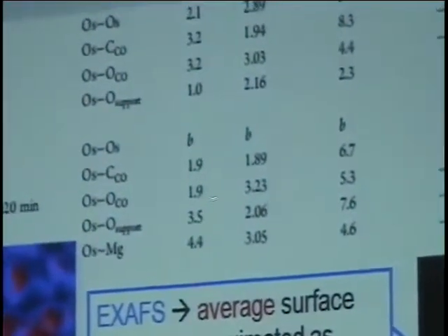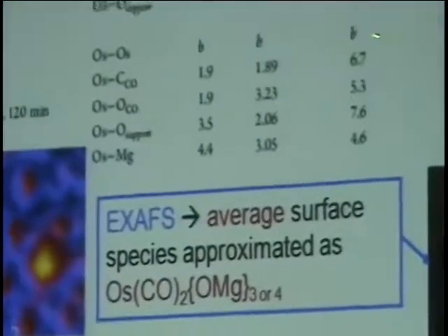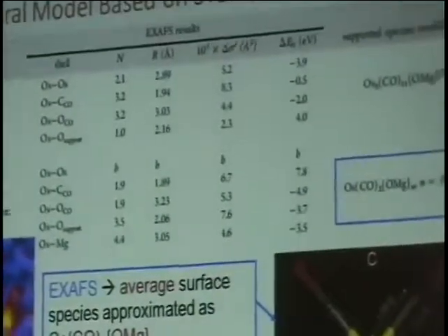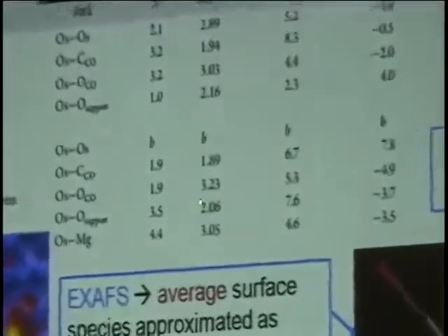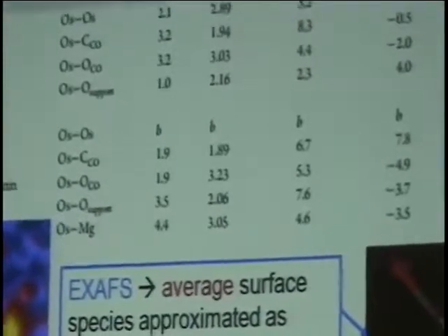And the key that we need to get beyond just the microscopy is the XAFS evidence. So let's go to the mononuclear: we get an osmium-oxygen coordination number over the whole sample, various faces of MgO, of 3 or 3.5. And so what we're inferring on this particular surface is that the value must be about 4. This is, of course, a model. And so we've got the distance, and it's the bonding distance, just what one expects from lots of similar samples. And so one can build a model with that osmium-oxygen XAFS distance. Remember, it's an average over the whole sample, all the faces, not just the face we're looking at, so it's an assumption, but it's chemistry.